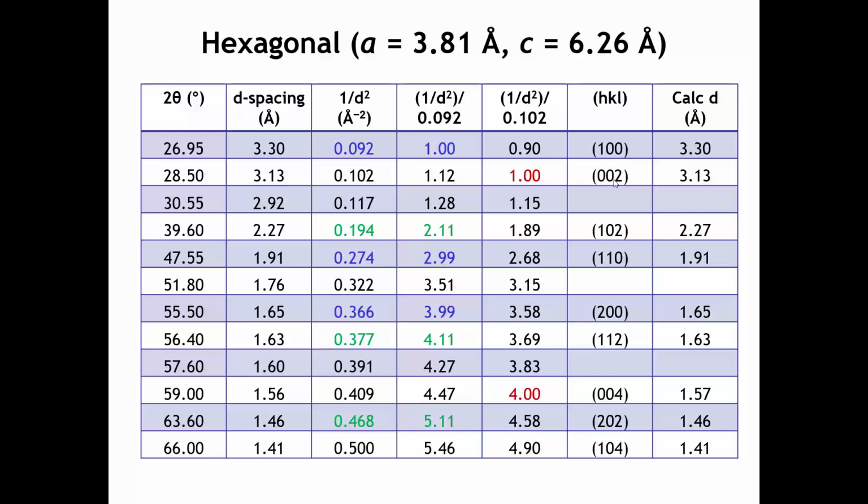Well, if we were to double the length of the c-axis, what that would do to the indices is everywhere the c value now also doubles. Right? So if you can imagine a unit cell and you had the 0, 0, 1 planes, those lattice planes would be 3.13 angstroms apart. But now if we were to make our unit cell 6.26 angstroms in height, then the spacing of those planes still should be the same, but they're not the 001 planes anymore. They become the 002 planes.